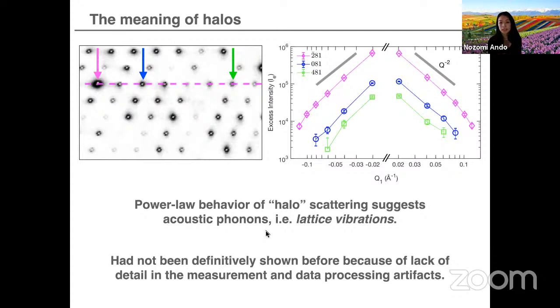And another thing that was kind of traditional in the biological diffuse scattering field was to mask out the Bragg diffraction, but in doing so, they were also masking out these strong halo-like features. And that could corrupt the sort of weaker signals in between. And the important thing is that, in scattering, you have to explain the dominant signal first, and then you have to explain the rest.